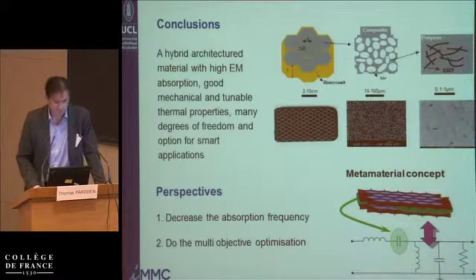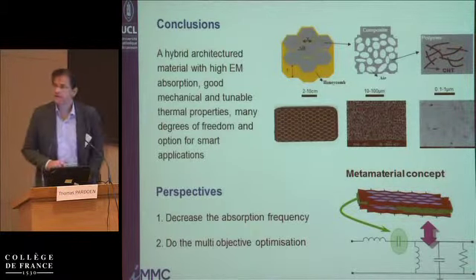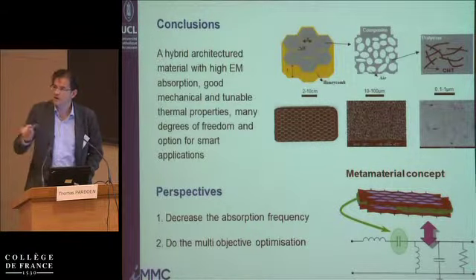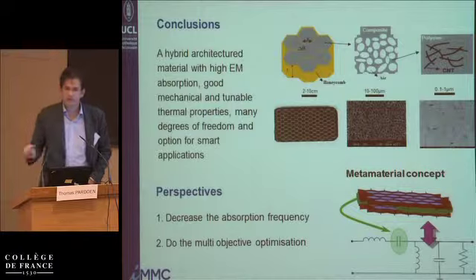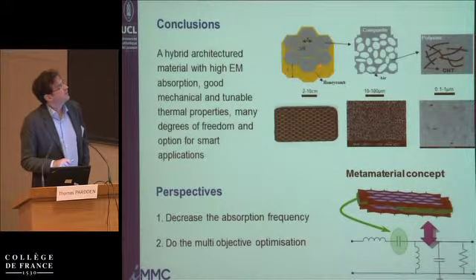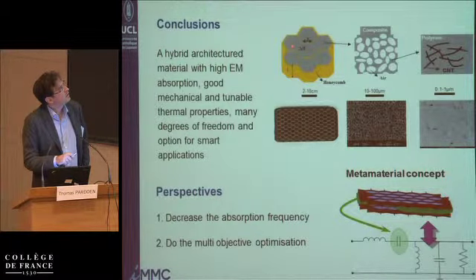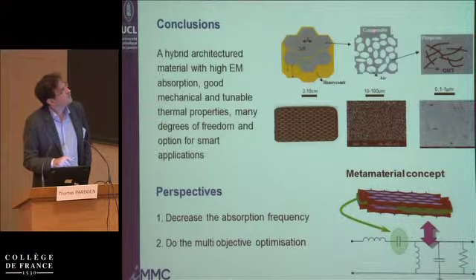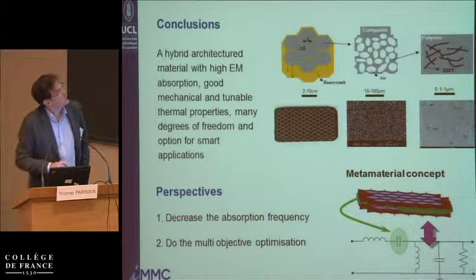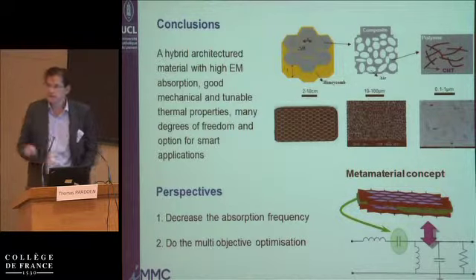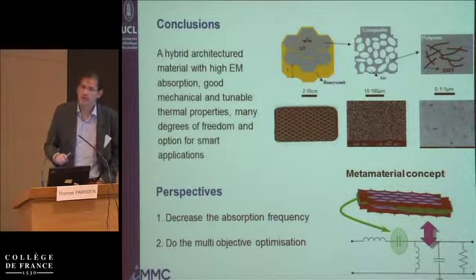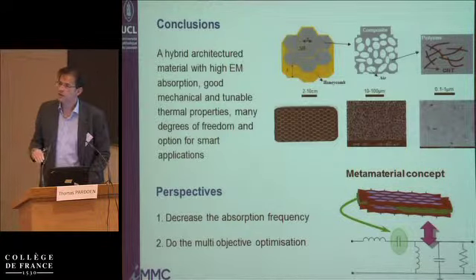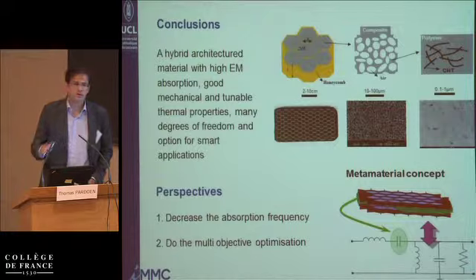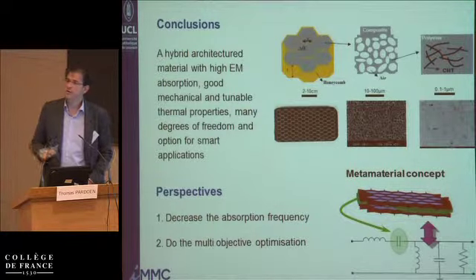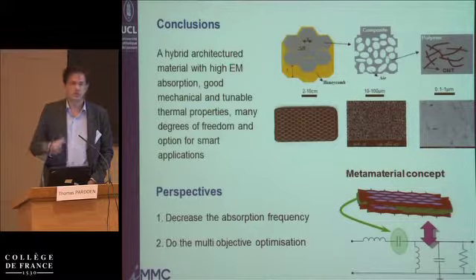Okay, as a conclusion, this is the hybrid architecture that I have presented, filling this gap in the dielectric constant electrical conductivity space, where you have a sandwich. The core of the sandwich is a honeycomb, and the honeycomb is made of a foam, and the foam itself is a polymer reinforced with carbon nanotubes. You have seen that the range of frequency in which we can absorb is above a few gigahertz. This is fine for many applications. Cellular phones, radar, many radars operate in the range above 2 gigahertz.